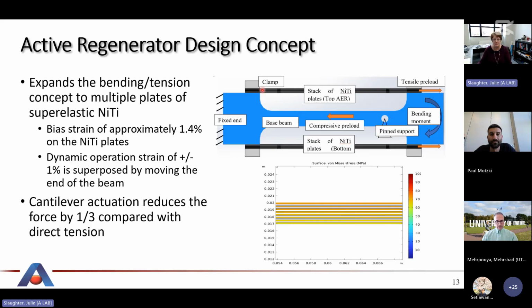One, it increases the amount of active material we have in our structure. But secondly, it makes a nice parallel plate heat exchanger. So this is a good structure for heat exchange. And to address the fatigue issue, we're operating at a bias strain and then operating a fairly low oscillating strain around that.